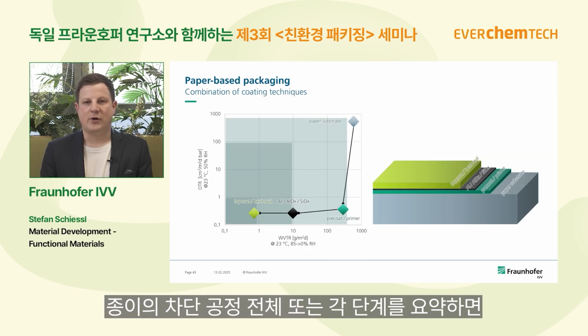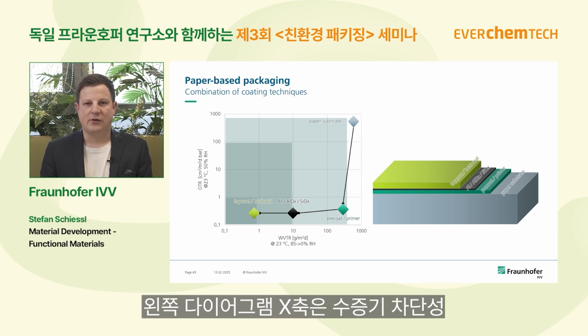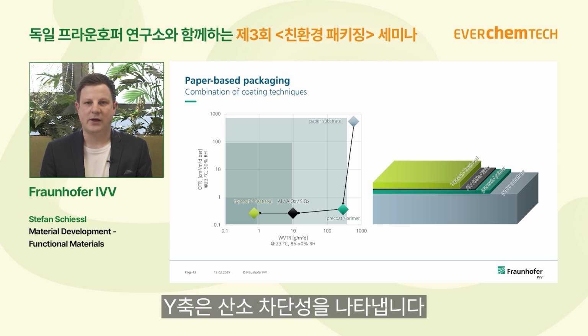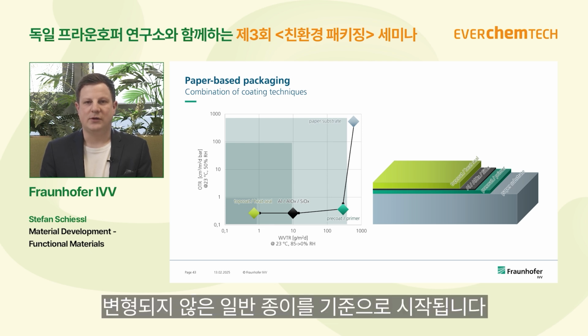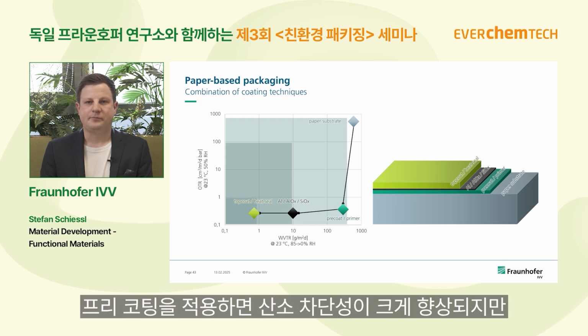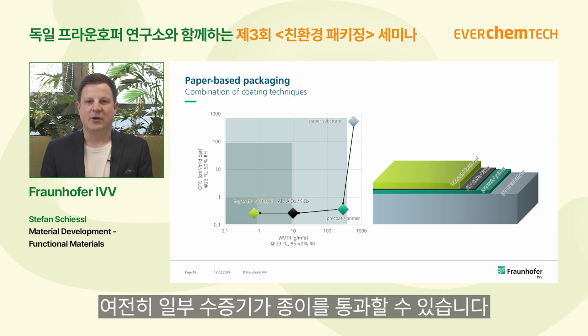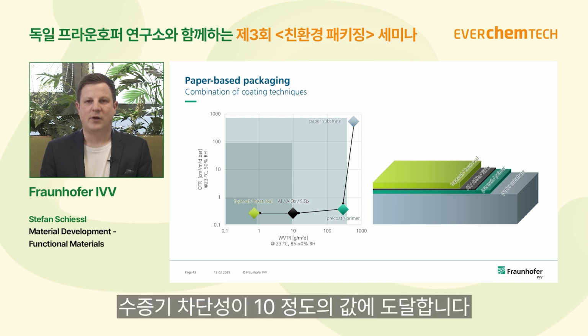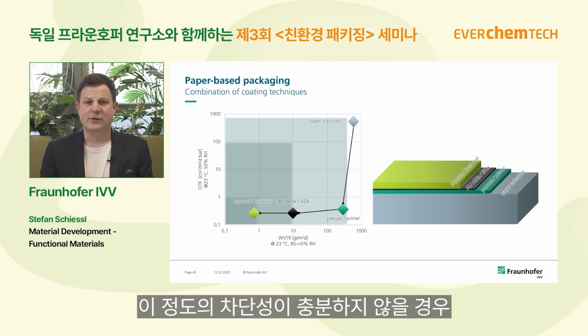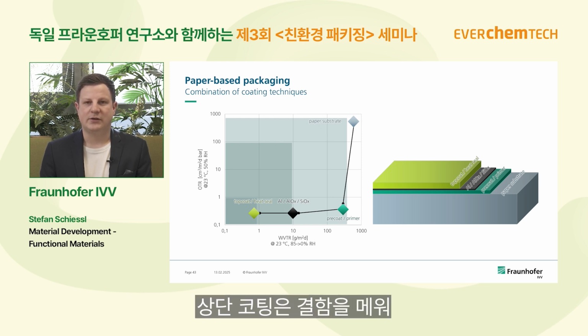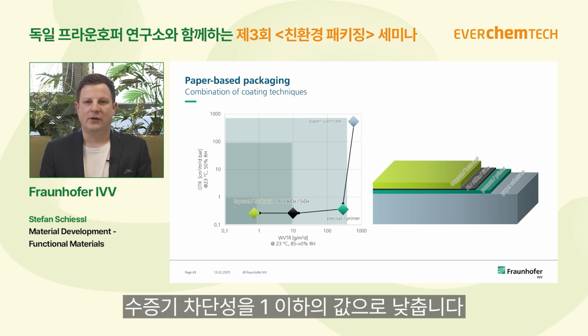So to summarize the whole barrier process on paper, or the single steps, we start with the left diagram where we can show the water vapor barrier on the x-axis and the oxygen barrier on the y-axis. We start on the right top of the value with a paper that is not modified. Then the pre-coating helps us to reduce the oxygen barrier significantly, but there is still some water permeating through the paper. If we do then a PVD coating, then the water vapor barrier is reaching a value around 10. If this value is still not enough for the paper and the application, then there is the possibility to do a top coating, which is protecting the PVD layer, and this top coating is filling any defects and therefore reducing the water vapor barrier to a value below 1.